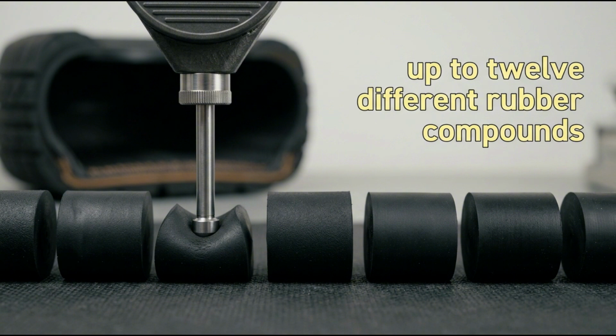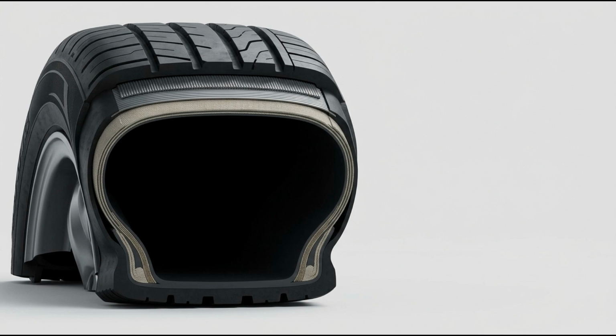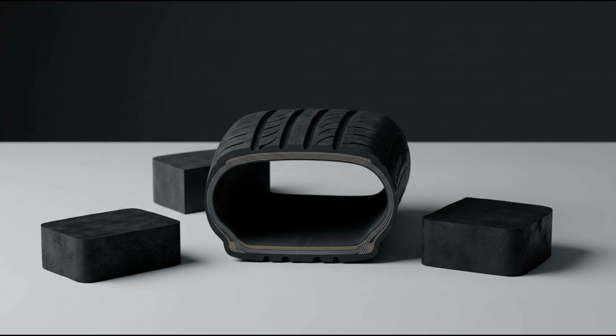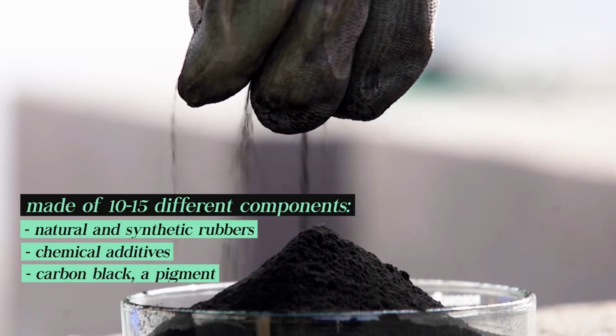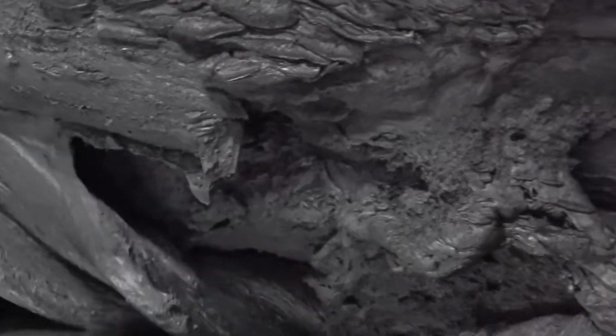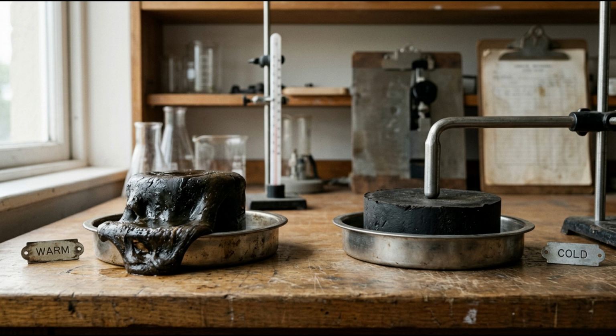The tread must resist wear while producing grip. The sidewall has to flex repeatedly without cracking. The inner liner needs very low gas permeability. Rubber around the steel belts must bond securely to metal. Other compounds manage heat, aging, stiffness, and the transitions between flexible and rigid regions. The factory is not searching for one perfect rubber. It is designing several imperfect materials that can work together. That challenge begins with a weakness that once made rubber unreliable.